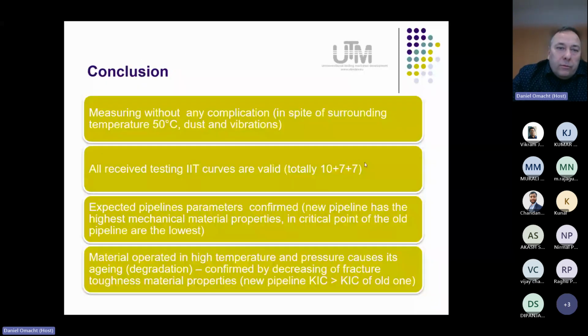The conclusion from this measurement was that in spite of the quite high surrounding temperature, about 50, maybe 55 degrees, with dust everywhere and quite some vibrations, we obtained by IIT totally 10 plus 7 plus 7, so 24 testing curves. And all curves were valid. You could see that the curves were not damaged, which was possible. All the curves could be used for evaluation. And the expected pipeline parameters were confirmed, because we expected that the mechanical material properties of the new pipeline would be the highest, and the critical point of the old pipeline would be the lowest.